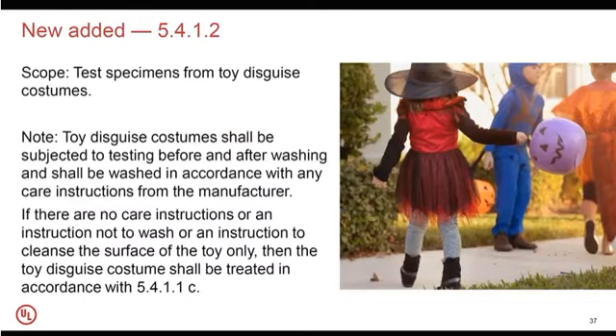So there is new added chapter 5.4.1.2, and the scope is to define how to create test specimens from toy disguised costumes. And there is a note that toy disguised costumes shall be subject to testing before and after washing, as I was saying at the beginning, and shall be washed in accordance with any care instruction provided by the manufacturer. If there are no care instructions, or an instruction to not wash, or an instruction to cleanse the surface of the toy only, then the toy disguised costume shall be treated in accordance with 5.4.1.1c, which is defining how to wash the disguised costume in this case, so all the labs testing are consistent.